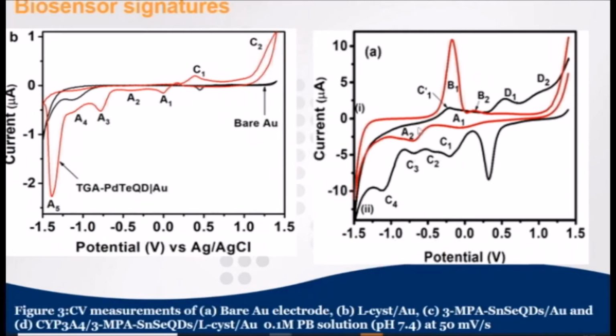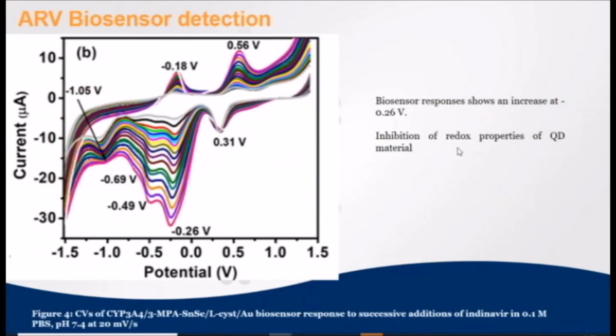And this one is actually responsible for the monooxygenation, because monooxygenation happens at the longer or more negative potential. So the peak that we are monitoring in this case is A1, because even here, although there is a slight shift happening, we can still see that yes, our enzyme is here. As I was saying, we are monitoring this region.